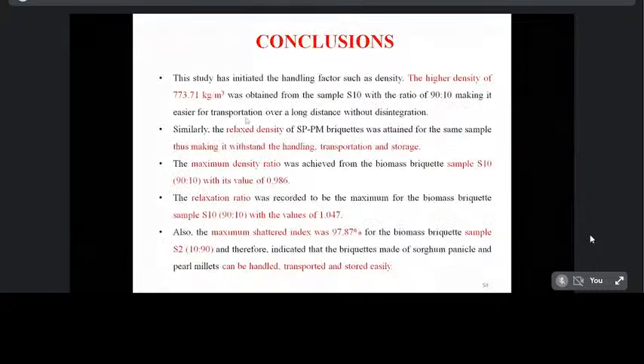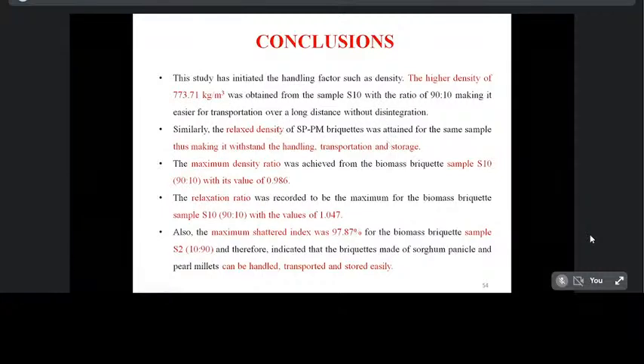So here is the conclusion. The study has indicated handling factors such as density. The highest density value is 773.71 kilogram per meter cube for the sample S10, and the relaxed density is also highest for the same sample. So the density is the main indication for transporting the produced biomass briquette from one place to another.